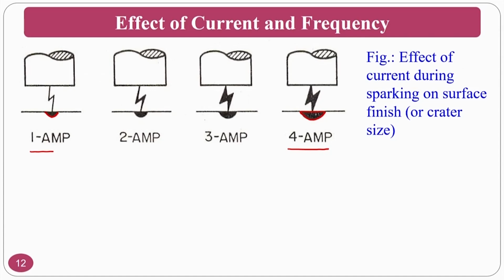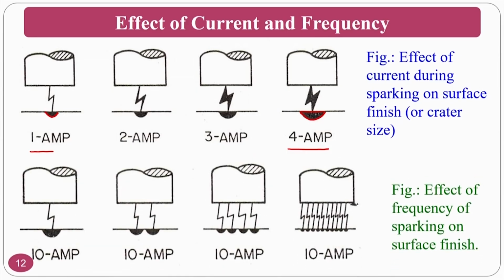Why I am saying is, in this condition your surface roughness will be like this. So, the surface roughness is very high in higher currents and surface roughness will be very low in low currents. At the same time, if you see the frequency of sparking effect on the surface, if at all you want to remove more and more material, then you have to go for high current along with high frequency. Okay. So, this combination will give you better MRR.